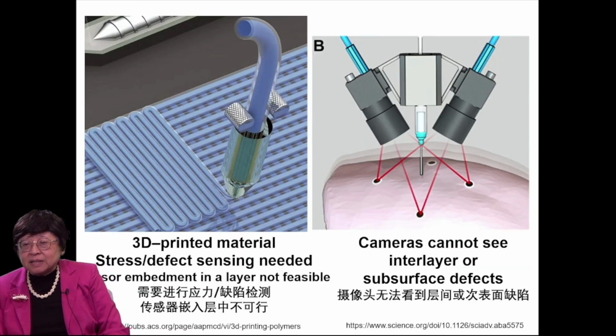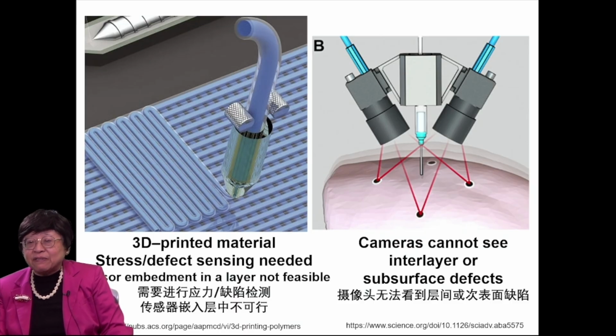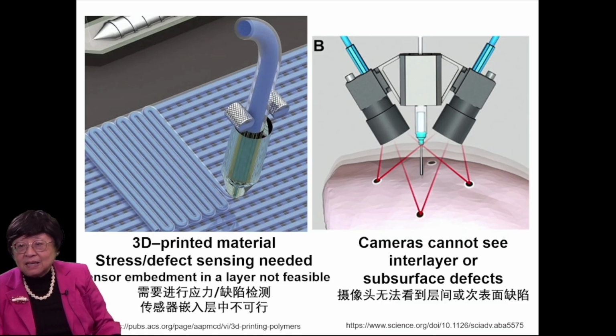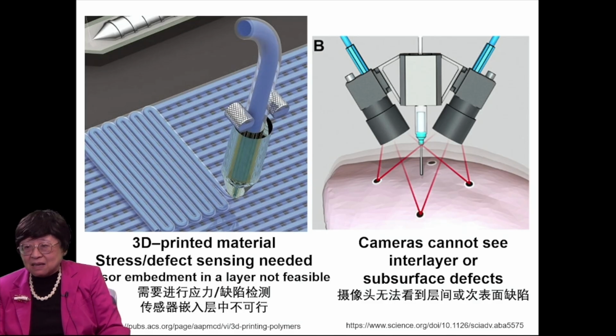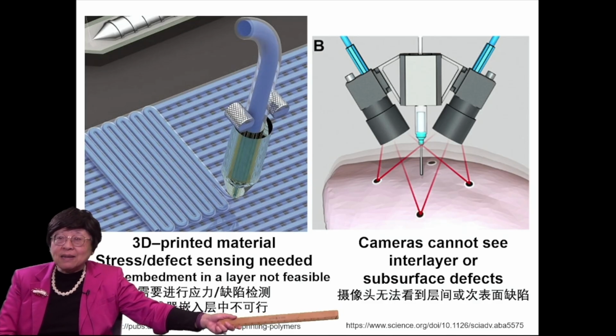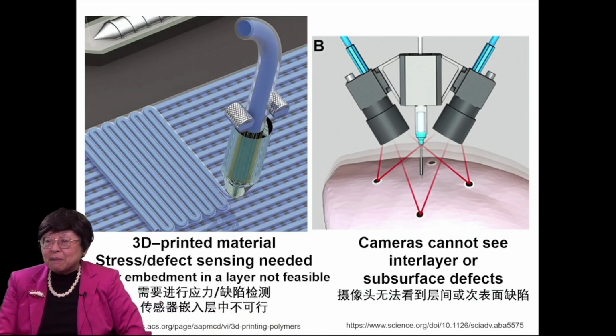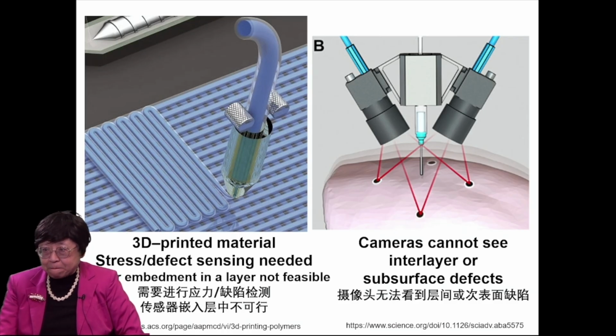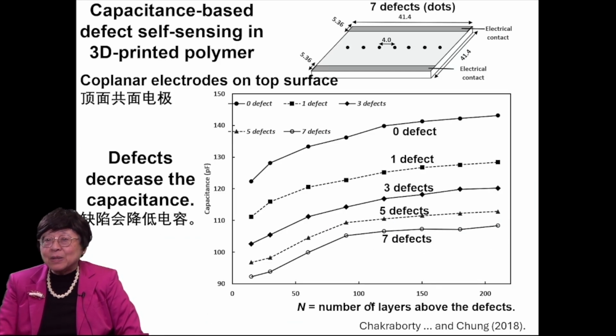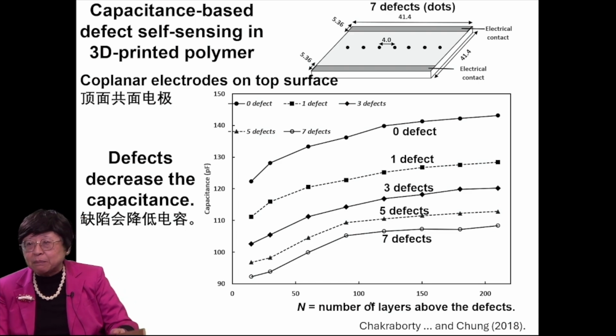In 3D printed material, the sensing of stress or defect is very much needed. Sensor embedment in a layer of the printed material is not feasible. It's just too tiny. Cameras are widely used during printing, but they cannot see interlayer or subsurface defects. But we can use capacitance-based defect self-sensing in 3D printed polymer.